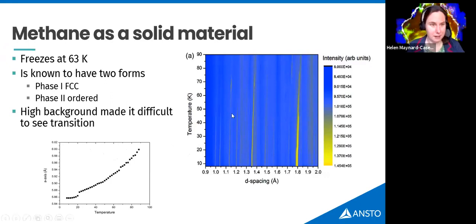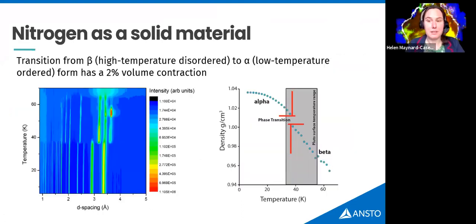I was able to look at methane, and again, I should say that this is hydrogenous methane. So we do get a larger background, which is why the data isn't going to be as pretty as the nitrogen data I'm going to show you, but you're still able to track the unit cell, and you can see that this jump here equates to a phase transition that's known, and this is phase two, and then it jumps to phase one. So that's less interesting in a way, because that's not over Pluto temperature scales.